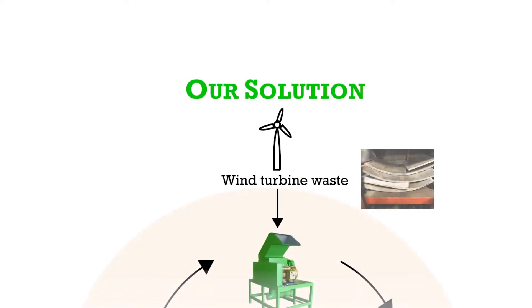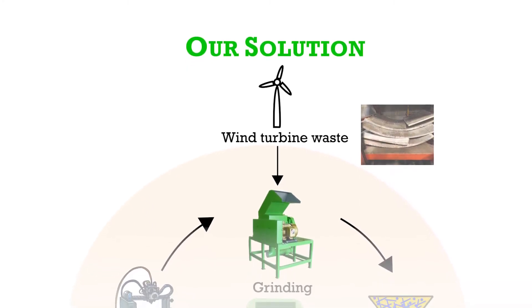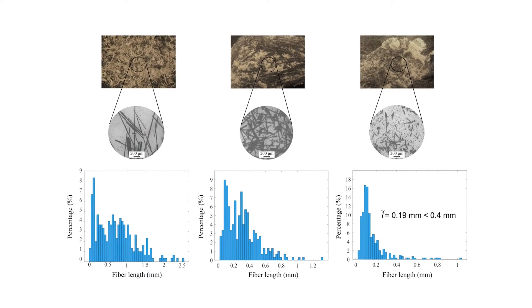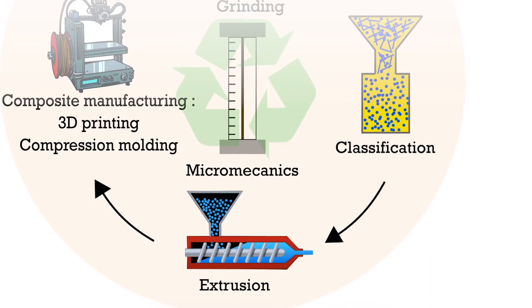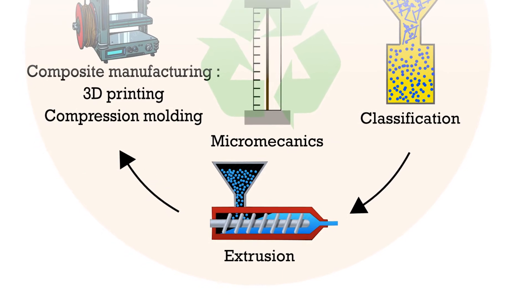Here's how we do it. Everything starts with the pre-processing of end-of-life wind turbine blades to manageable sizes for the grinding stage. The grinder reduces the size to predefined categories and a sieve shaker classifies the output from the grinder. Different output categories are suitable for different applications. For instance, the fine short fiber recyclets are fed into a twin screw extruder to reinforce the pure polymer and improve performance and mechanical properties.